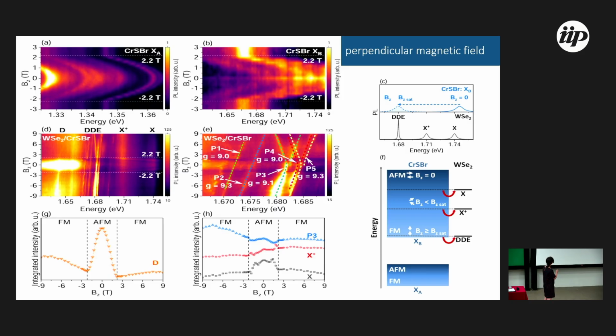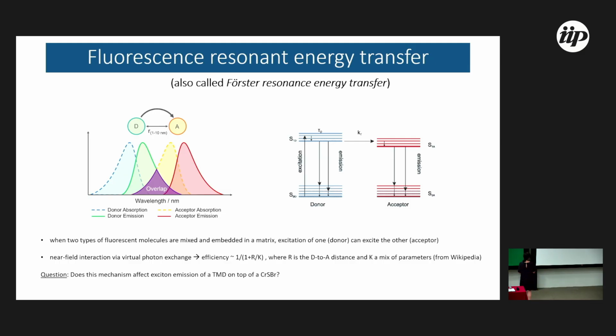If you compare, this is very similar to the change of energy with magnetic field for the B exciton. I will go briefly because I don't have time. The main explanation is here. I can shift this B exciton more, and it can be in resonance with the exciton, trion, and these sharp emission peaks. There is an effect that people who work with optics know well, which is energy transfer. This effect can change the intensity, because you can have a resonance and transfer to another material.